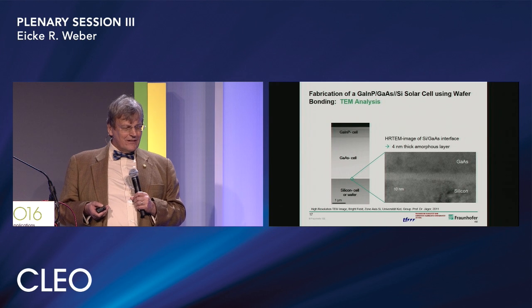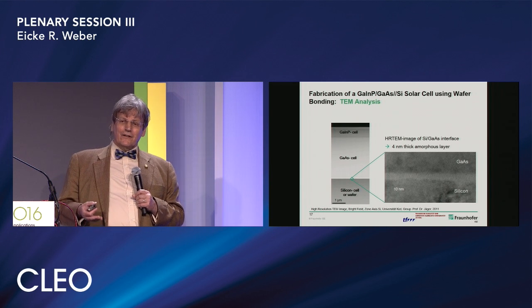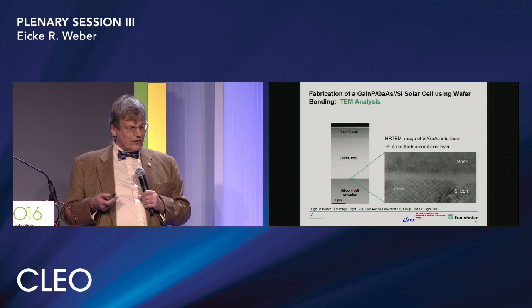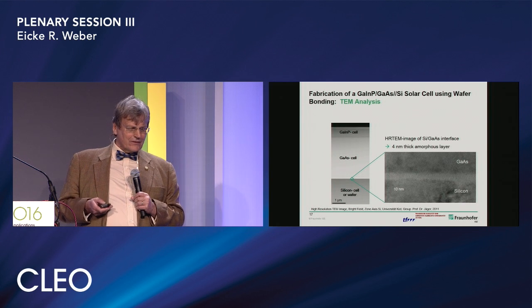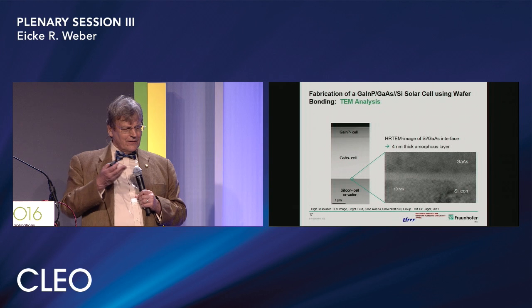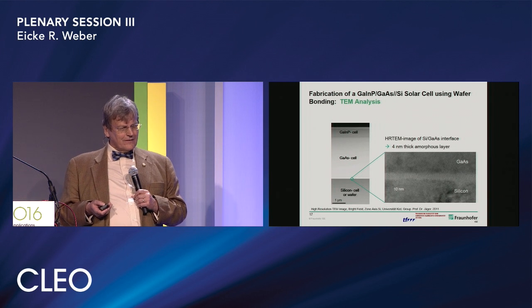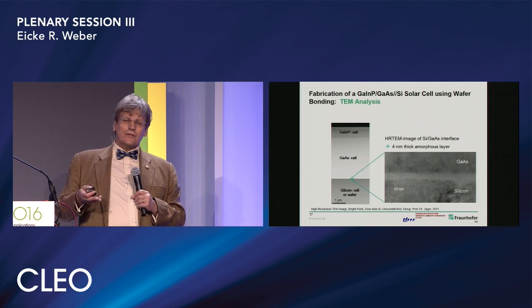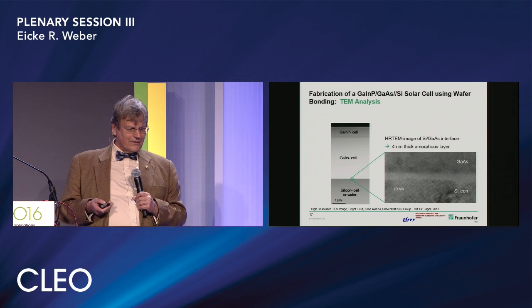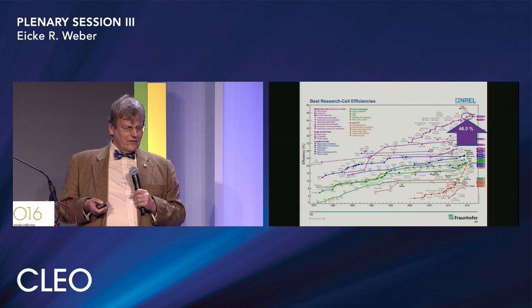And the key issue there is using wafer bonding. We avoid the problems of the growth of 3-5s on silicon. So wafer bonding, and you see here the cross-section, that this interface really does not introduce any defects in the adjacent layers. This is really a key factor.